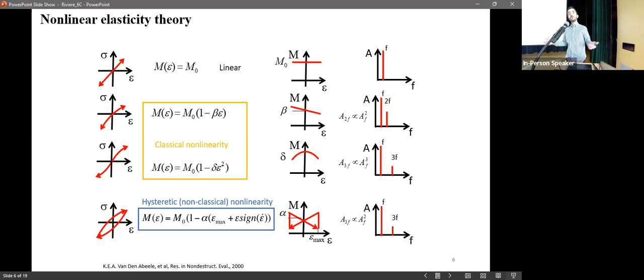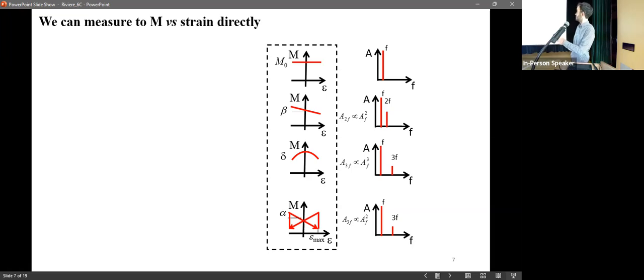So one thing that we could do is to send waves inside a rock sample and measure the amount of harmonics. What type of harmonics? How do they grow with the amplitude of the fundamental? So that would be this thing here. But what we have been using most recently is basically to try to measure in the lab changes in modulus as a function of strain directly. If we are able to measure this directly, then that gives us much more information about the physical mechanisms at the micro scale.